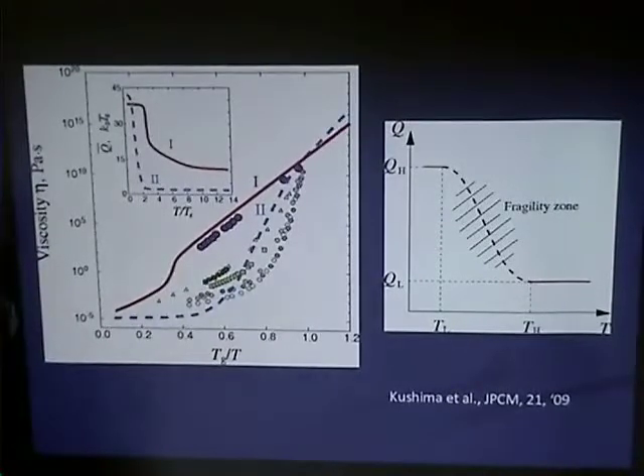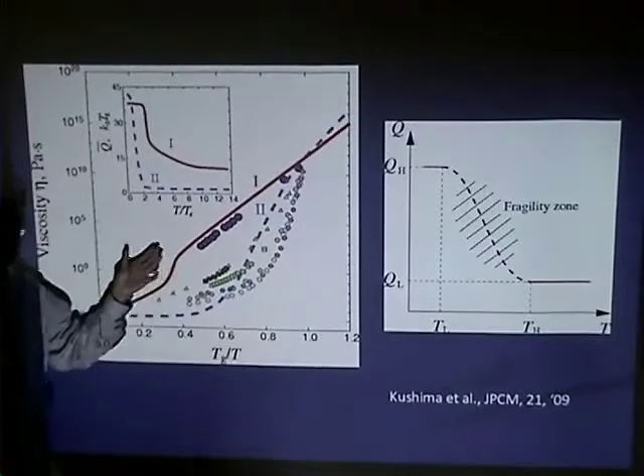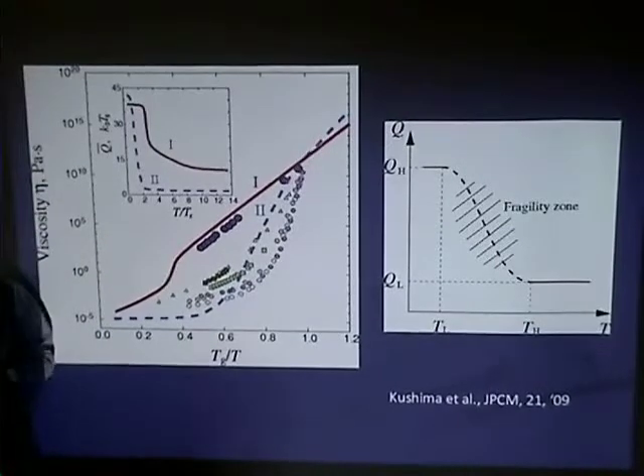Because you can have very, very low barriers, and you still need to hop out of them because you're never going to be stuck. If you have a perfect crystal that's very, very deep, then once you fall in, you don't get out. But so long as you have a glass, it's metastable. Eventually, if you wait long enough, you can hop out. To get that kind of activation, you cannot do it with inherent structure. You need something that allows you to sample.